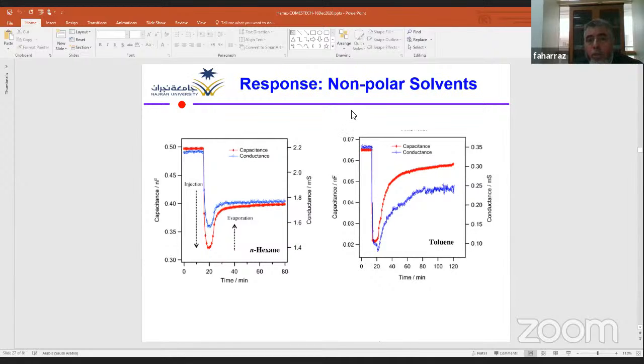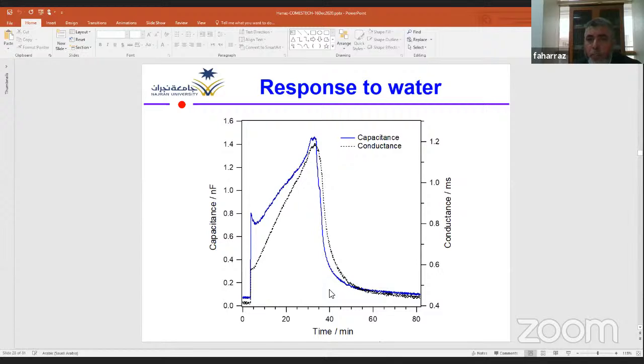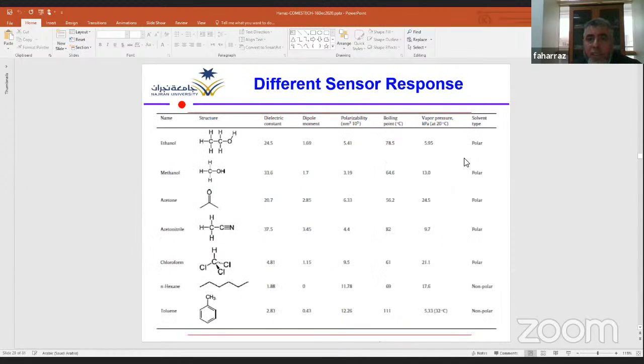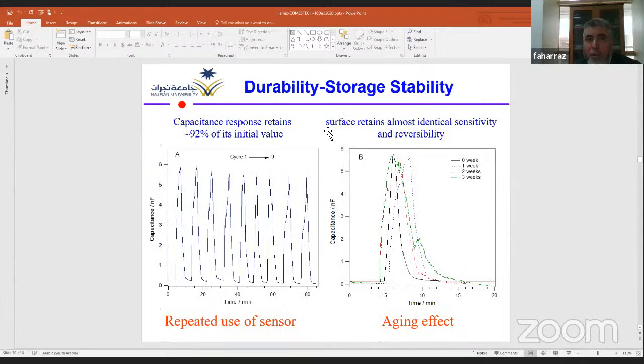When we examine the response towards some non-polar solvent, the response of the device is completely opposite to the polar one. This depends on the different physicochemical properties between polar solvent and non-polar solvent. Our device also responds to water, and this is very interesting because our device can be utilized to detect some aqueous analyte. This table shows the different sensor responses with polar and non-polar solvents, which is explained by the different dielectric constant, dipole moment, and polarizability of the polar or non-polar solvent.